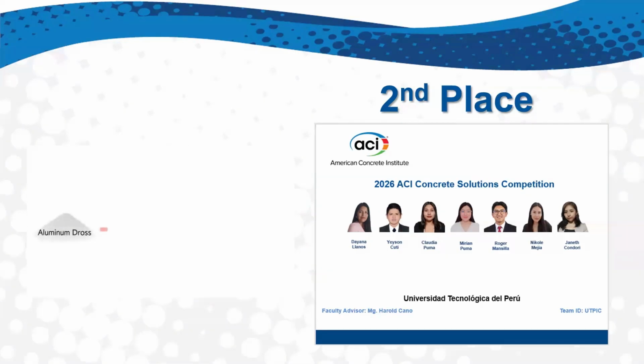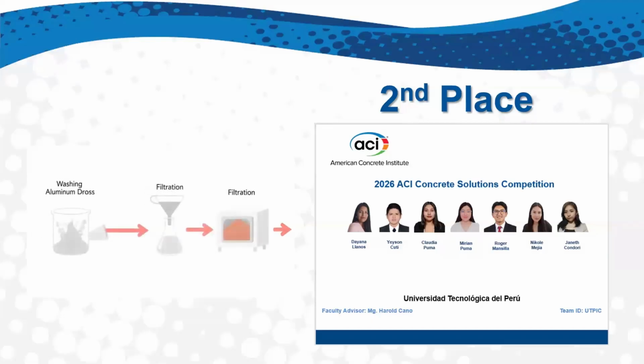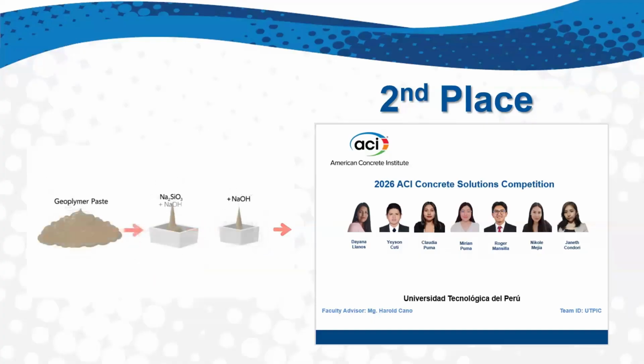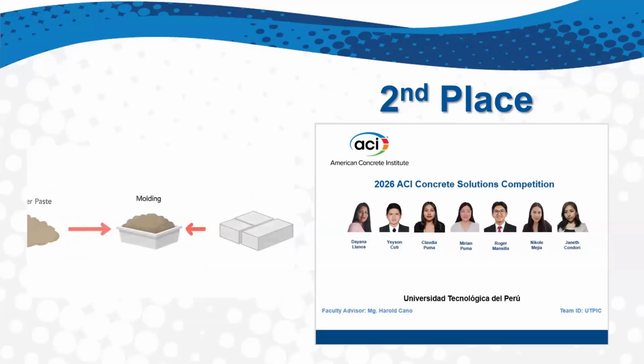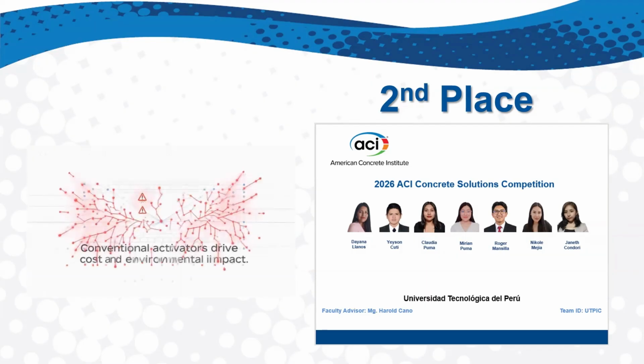But it's not all about the fines, as the activators, which allow the reaction to occur and transform the combination of rice husk ash and brick powder particles into a structural material, are essential for the system to truly function as a whole. Without them, there is no matrix, there is no cohesion, and therefore there is no brick. Conventional activators, such as sodium hydroxide or silicates, concentrate a large part of the cost and environmental impact. As long as there's no continuity, sustainability will end up breaking down.